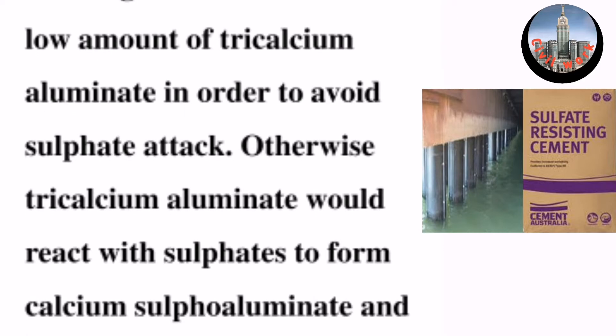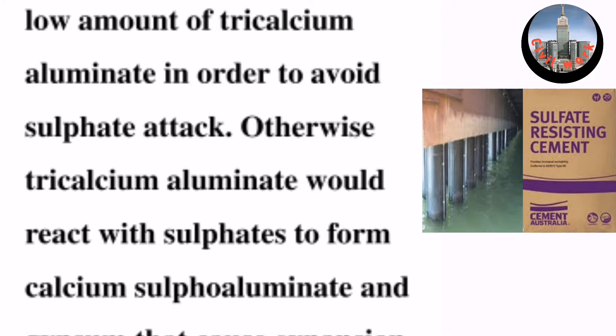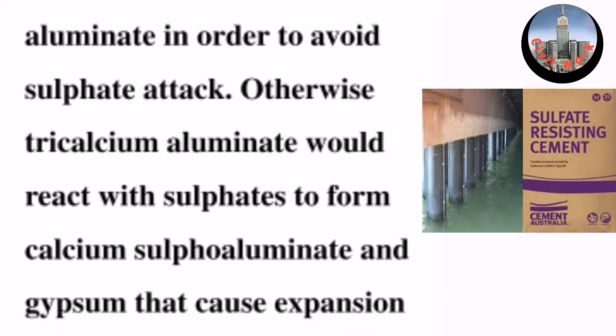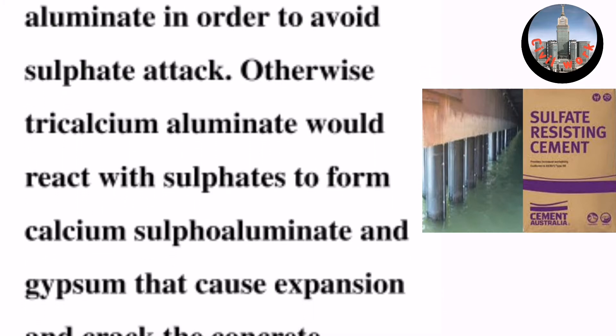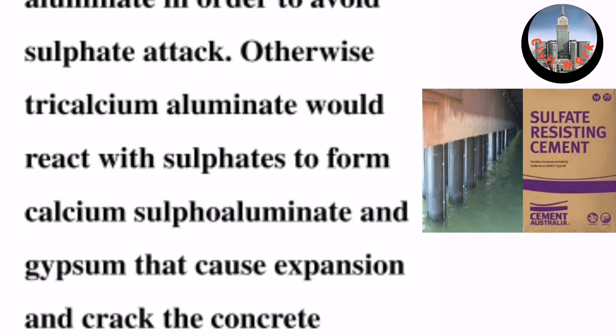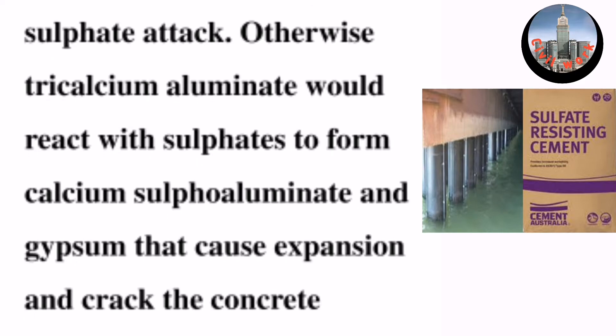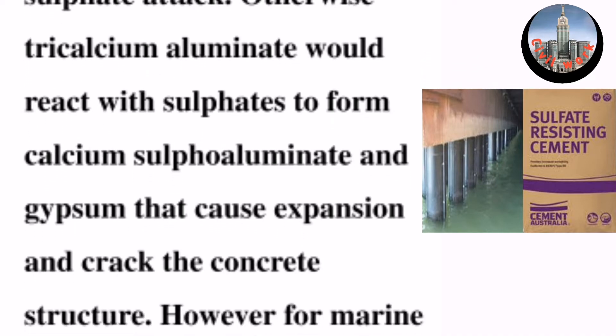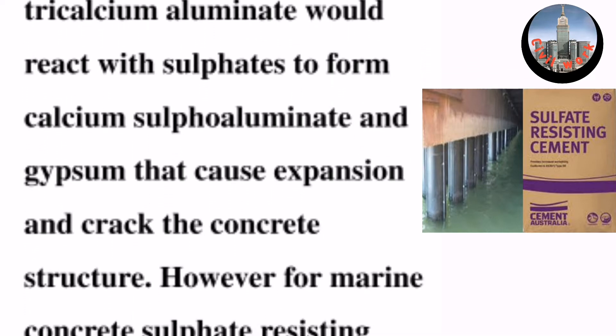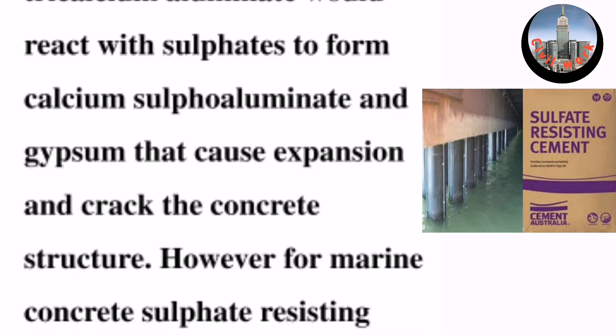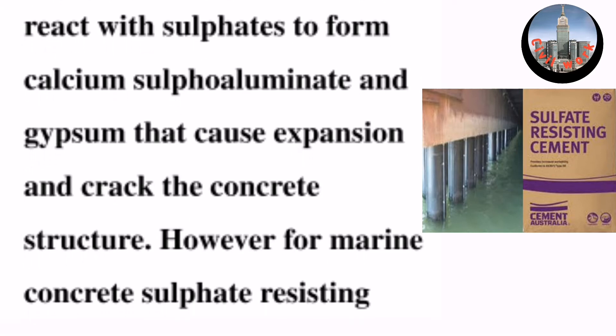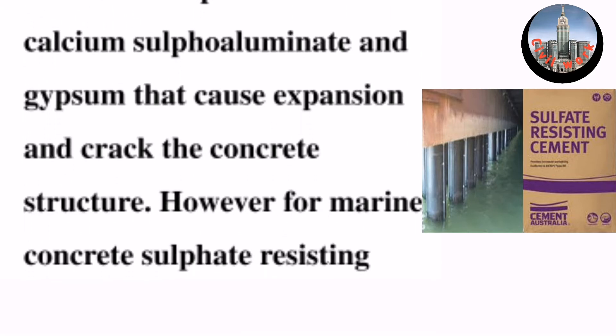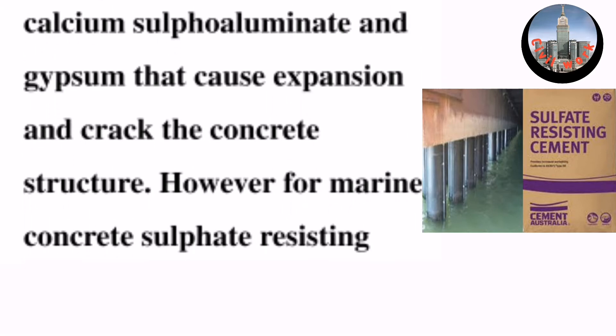Otherwise, tricalcium aluminate would react with sulfates to form calcium sulfoaluminate and gypsum, which cause expansion and crack the concrete structure.